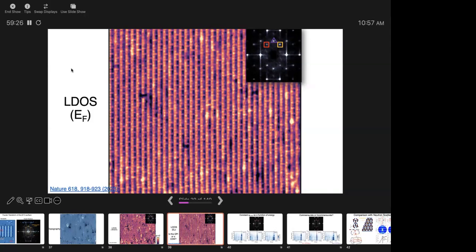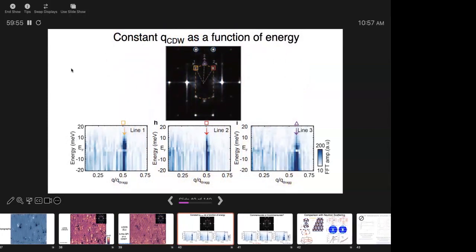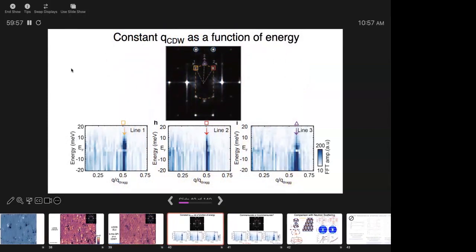You see almost every second tellurium atom is bright. It's not perfect. And the reason it's not perfect is not that it's disordered. The CDW is really nicely ordered. It's because these 3 CDW peaks are incommensurate. And so you see them nicely only when they actually lie commensurately on the lattice. Whenever they're off the lattice, you don't see them very well. So there are these three incommensurate peaks, and the question is, is this quasi-particle interference or is this a charge density wave? And to answer that question, you can look at the energy dependence.